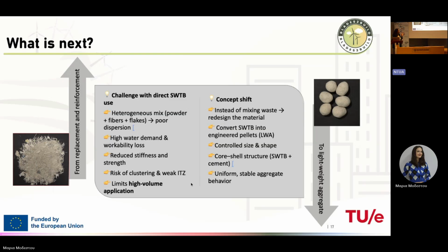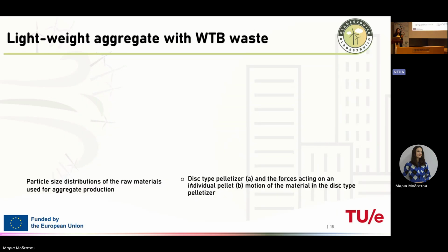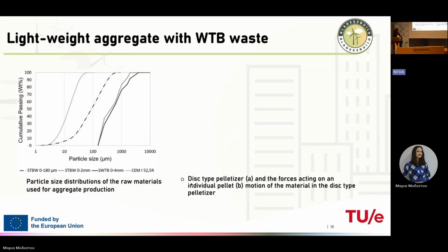Instead of mixing waste, let's redesign the material. So we convert these shredded wind turbine blades into pellets, lightweight aggregate, with control. So we can control more here. We can control size and shape. We basically sieve the waste to control the highest particle size. We have a core-shell structure because we use cement in a small amount, and we have uniform, stable aggregate behavior. So no unexpected things.